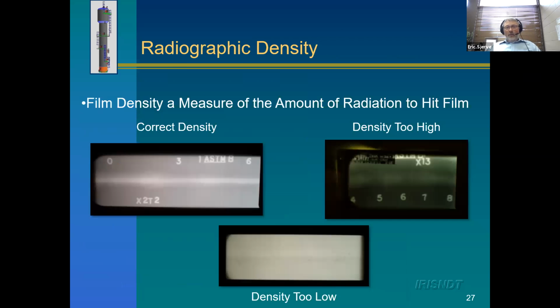With radiography, there's something called radiographic density. You want the grayscale to be right. On the picture on the bottom, the density is too low, so it's not had enough radiation to properly expose it, and it's white. You just can't see much in it. The one on the top right has been exposed with too much radiation, so it's too dark, and we can't really interpret it. The ASME code tells us what the correct density is, which is the one on the top left, and you can see a lot more in that image because it's exposed properly. That's radiographic density.